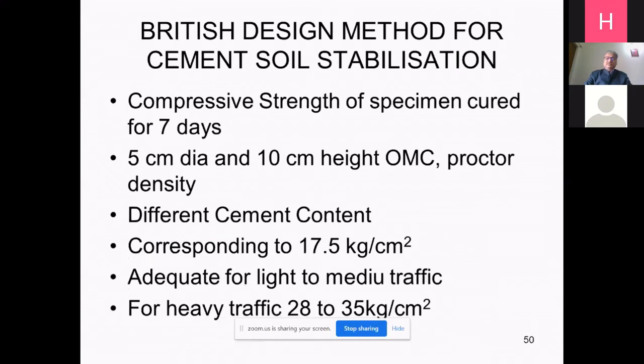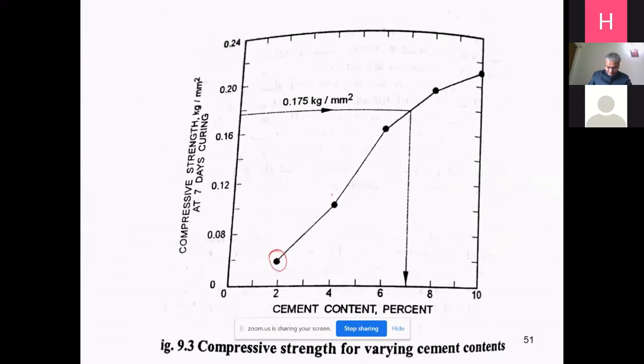There are two methods. One is the British design method for cement soil stabilization. You have to make samples like this, 10 centimeter height and 5 centimeter dia. Different cement contents are taken, and then you have to find out the compressive strength, and the value corresponding to 17.5 kg per centimeter square is basically the required value. You can see here, these are the different points showing different cement content and different compressive strength. When it comes to 17.5 kg per centimeter square, or 0.175 kg per mm square, that value gives you the required cement content.